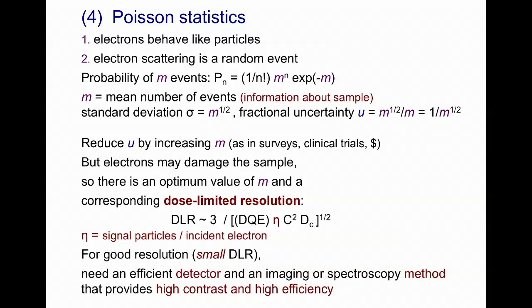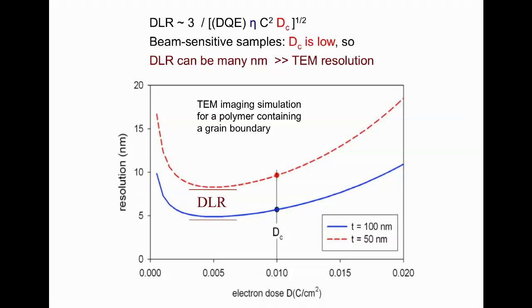The remaining DLR factor is the radiation sensitivity of the specimen, represented inversely by its critical dose DC. If we expose a TEM specimen to electrons and form an image, the resolution starts off poor because we have few electrons and bad statistics. With increasing electron dose, the dose-limited resolution improves, but beyond a dose of the order of DC, the resolution starts to get worse again because radiation damage is destroying the original structure and reducing the image contrast. For most biological specimens, this dose-limited resolution is many nanometers, far worse than the electron-optical resolution of a TEM. For a metallic specimen, the situation is much better. The dose-limited resolution may have subatomic dimensions, and the actual resolution is limited by the electron optics.